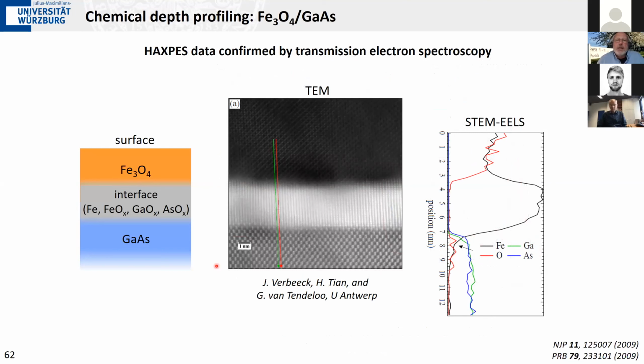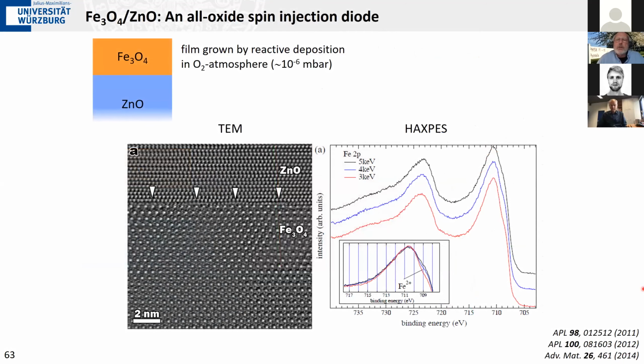such a transistor. And this is confirmed here by transmission electron microscopy. Here you have the gallium arsenide, here you have the magnetite, and here we have a range of basically metallic iron here. So it doesn't get oxidized, or the oxide that you try to pump in here gets absorbed in the gallium arsenide. And you can see this also when you do the chemical analysis by STEM-EELS as you go through this interface region here.